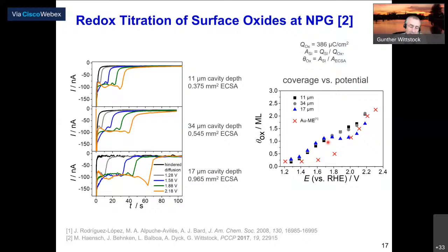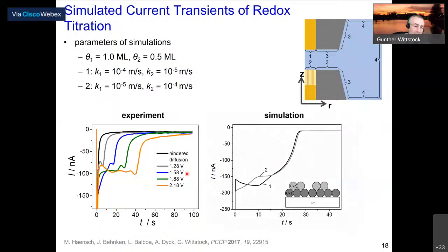So that is a very interesting procedure, and it does not depend on the stripping of an adsorbate like in the situation which I showed you before. Now, if you look more closely at these transients, we can observe something very strange. So initially the current falls off, yeah, that is understandable, but then it goes through a minimum, then rises again, and then falls finally.